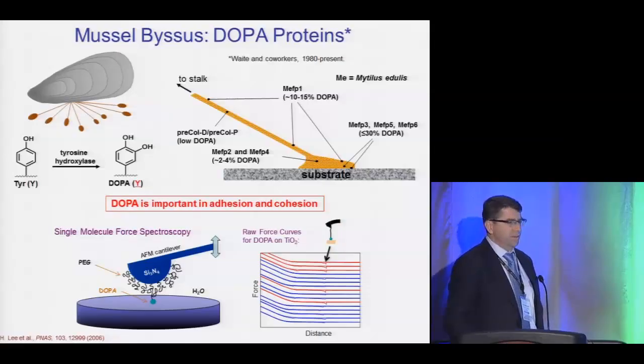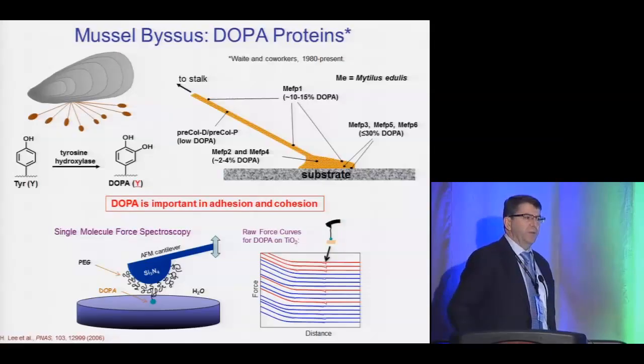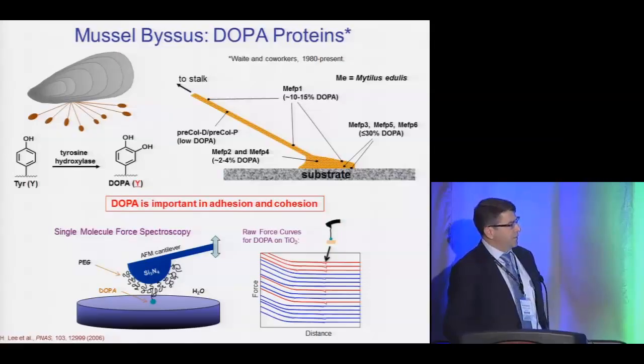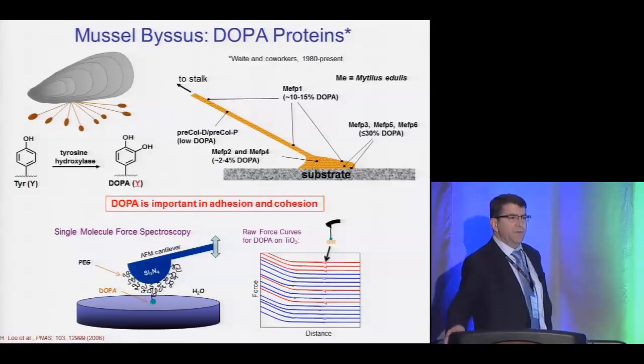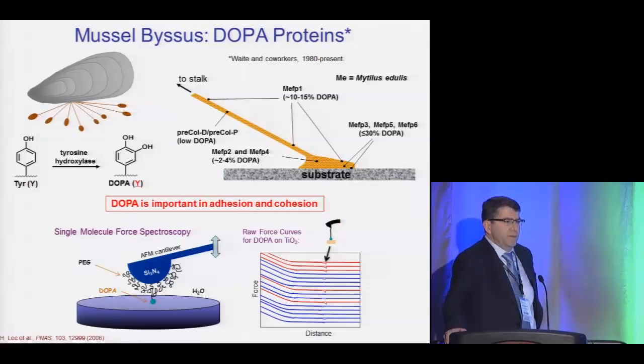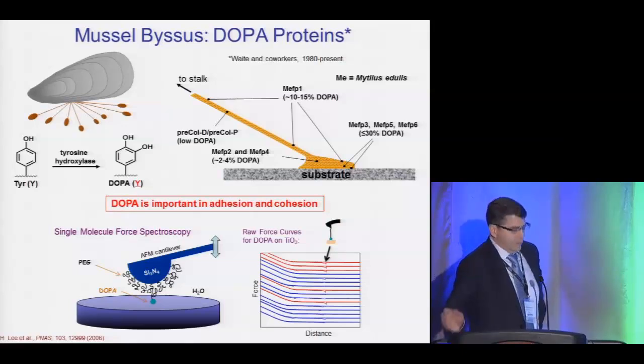we put the cantilever down on the surface and then pull away, and we want to know how much force it takes to take that molecule off the surface. And these are some example force curves. These are essentially the raw pieces of data. The feature that we're interested in is in this area right here. It's fairly small, but these are fairly large peaks as single molecule force spectroscopy goes. And you see that some of these force curves are shown in red, others in blue, because the ones in red have a much higher pull-off force than the ones in blue.